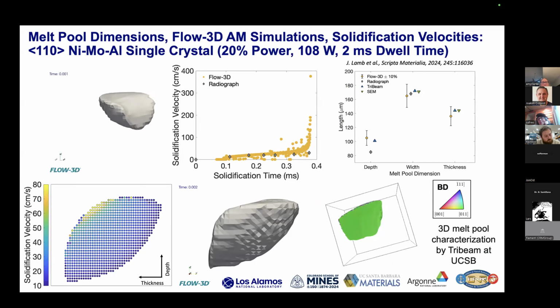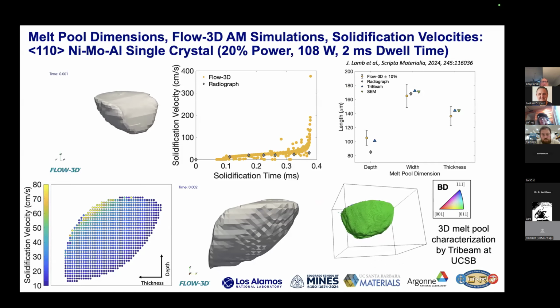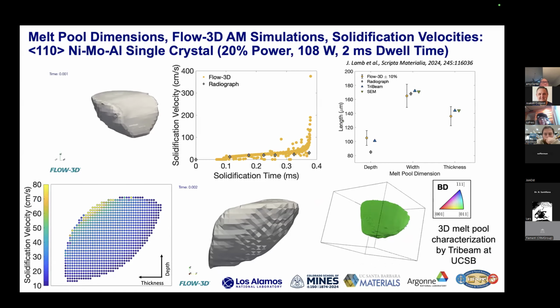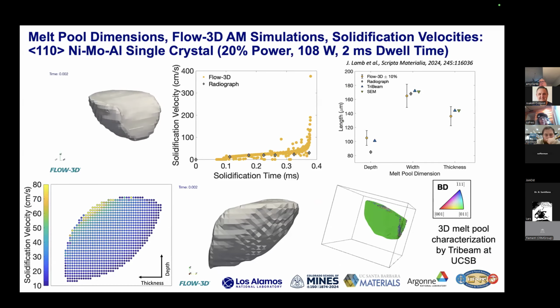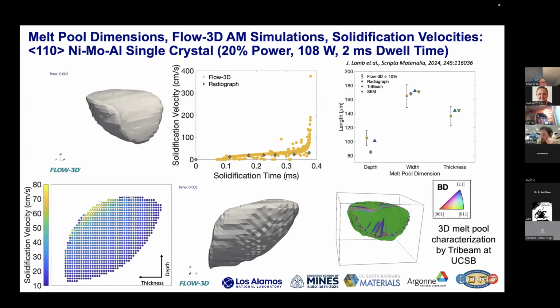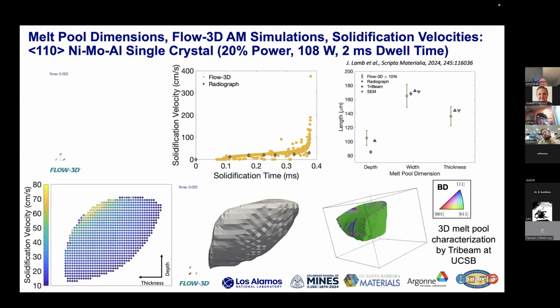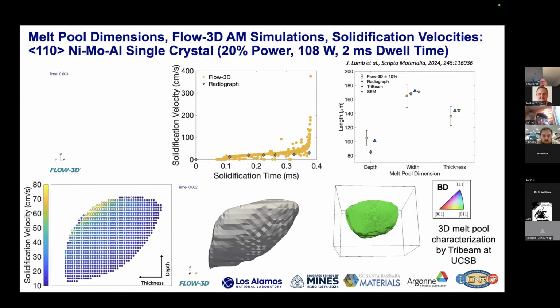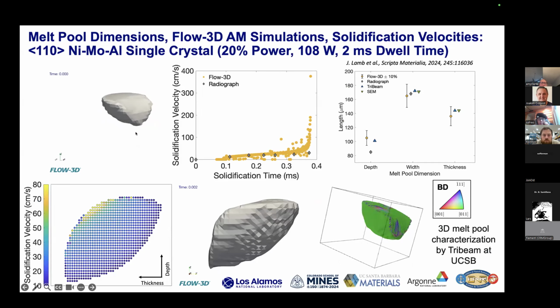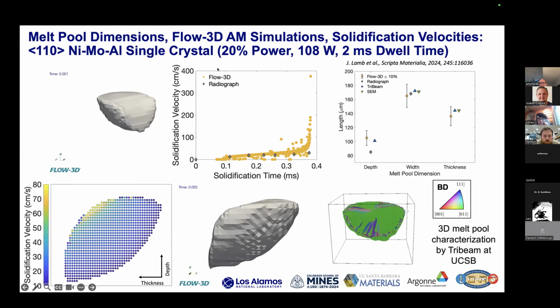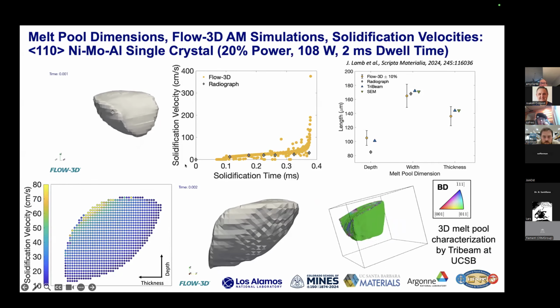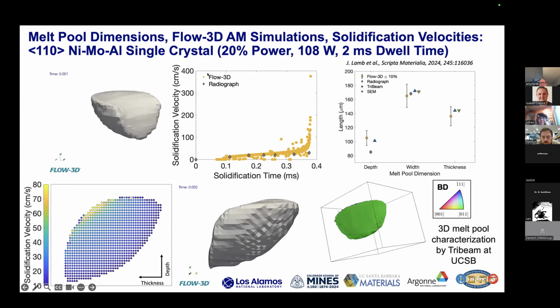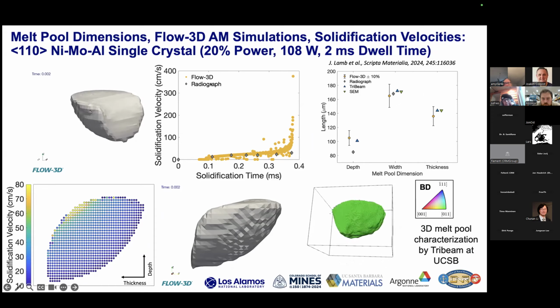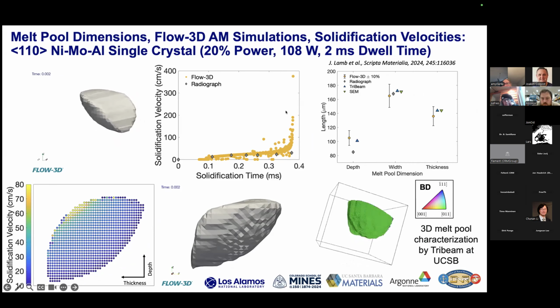So moving forward to model some of this kind of data, we felt like we really needed a handle on not only the solidification velocities, but also the thermal conditions that are experienced in the melt pool. So to do that, we started doing Flow 3D AM simulations. And so here we're actually doing a set of simulations for one of these spot melts and comparing head to head the velocity versus time of the Flow 3D CFD simulations to our radiography, which match well.